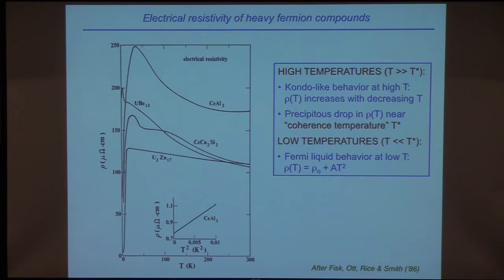Okay, so let me just show you a few examples. This is resistivity versus temperature for CeAl3, UBe13, CeCu2Si2, and U2Zn17. And so you see as you lower the temperature, you get this dramatic increase of resistivity that's reminiscent of a Kondo effect. And then it reaches a maximum and drops precipitously as you go into this highly correlated ground state, where these ions, which at high temperatures were carrying local moments, now become non-magnetic and thereby become equivalent, and that then causes the resistivity to drop to a low value.